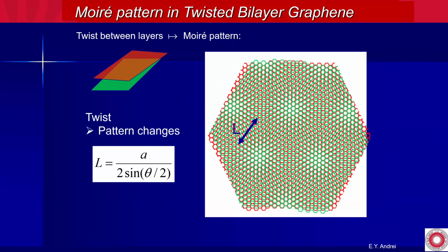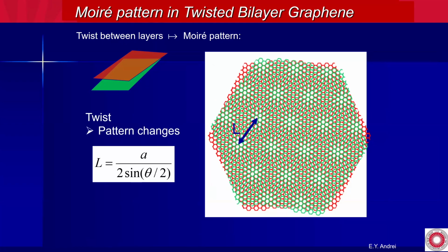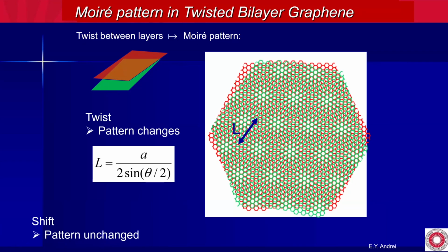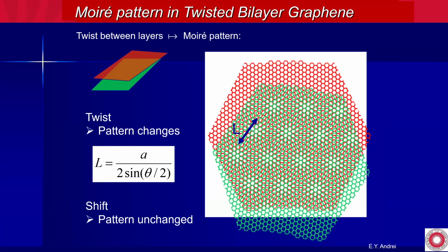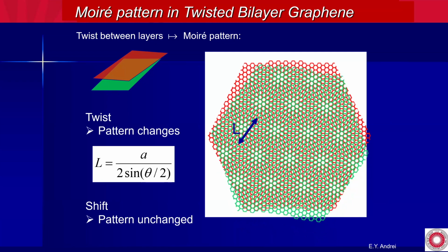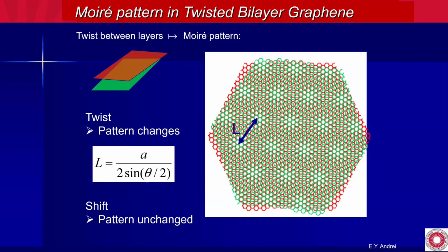But a little bit about Moiré. We all know that when you put two patterns together with a twist, you get a Moiré pattern with a super period. It's inversely proportional to the twist angle. What is maybe less known is that if you shift the layers, as you see here, the pattern doesn't change. And this is a real gift to experimentalists because it doesn't matter how you align them. All that matters is the twist.